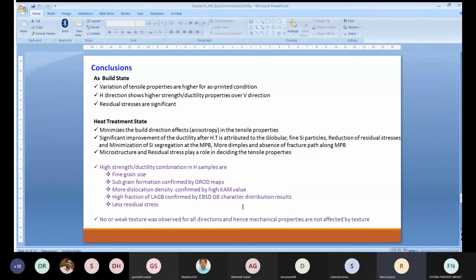Here you have a bimodal grain distribution with very fine grain sizes, and a larger amount of subgrains formed inside the grains, which were validated through the kernel average misorientation map and GROD, that is, grain reference orientation maps. More dislocation density was also confirmed through high KAM values, and a high fraction, about 50%, of low angle grain boundaries was confirmed by EBSD grain boundary character distribution results. And of course, low residual stresses also help improve the strength and ductility. We found that no texture or very weak textures were observed in all the directions. Hence, the mechanical property of the AlSi10Mg is not affected by the texture. So these are the significant conclusions we drew from our results.